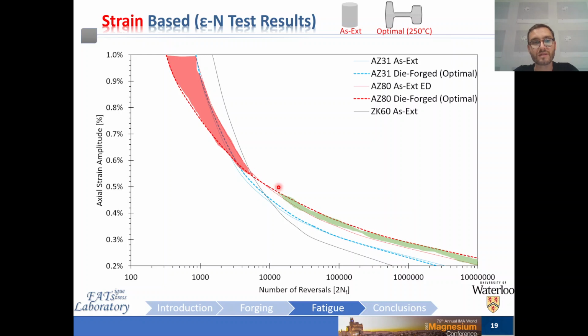However, there exists a transition point around 10,000 reversals where the effect of strength and ductility modification changes. At lower strain amplitudes, the loading is predominantly elastic, and the enhanced ductility causes an increase in fatigue life, as you can see here highlighted by that green region.